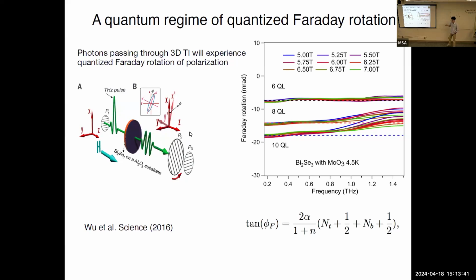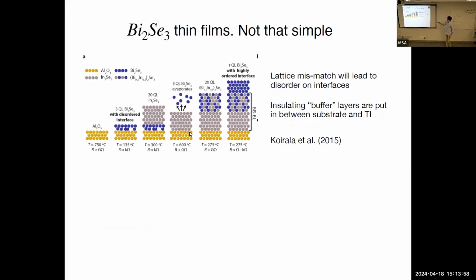When I said bismuth selenide, normally you just think this is just a slab of bismuth selenide and nothing else. But I just want to give you some sense of how people actually realize that thing, so that it's actually clean bismuth selenide. It has no surface disorders or anything else. So in this case, this same bismuth selenide which was measured is actually grown on top of some dielectric substrate, sapphire in this case. It actually has to be grown with caution, because usually you can't just grow material A on material B, because they usually have a lattice mismatch, and if there is a lattice mismatch, it will produce a strain, and you can never get a clean bismuth selenide. So you have to have these intermediate buffer layers, and they have to be insulating.